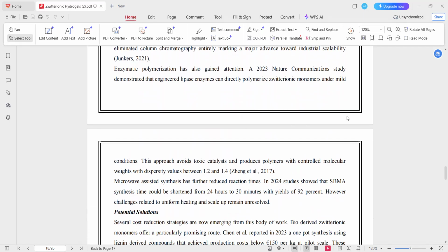Another promising approach is enzymatic polymerization. A 2023 study published in Nature Communications showed that engineered lipase enzymes can directly polymerize zwitterionic monomers under mild conditions. This process avoids toxic metal catalysts and produces polymers with controlled molecular weight distributions, with dispersity values between 1.2 and 1.4, which is highly desirable for reproducible material performance.